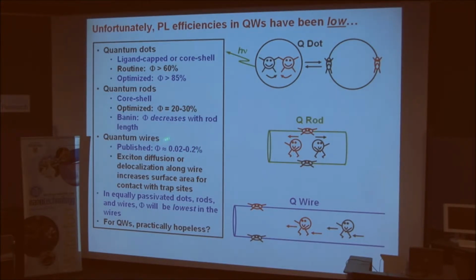Now, here are the efficiencies currently published in the literature for quantum wires. These are devastatingly low, 0.02 to 0.2%. And obviously, the case for wires is severe because now electron hole pairs can make excursions along the long axis of the wire looking for trap site defects where they can become trapped. So obviously then, in equally well passivated dots, rods, and wires, the efficiencies will always be lowest in the wires. So the question is, is this problem so severe that it's practically hopeless to think about wires in which carriers and excitons can be efficiently transported? It's a big problem, and maybe it's unsolvable.